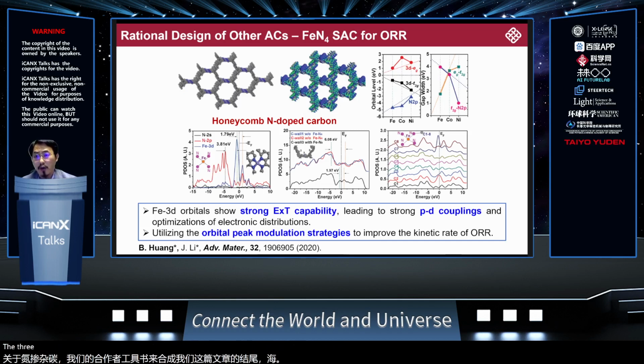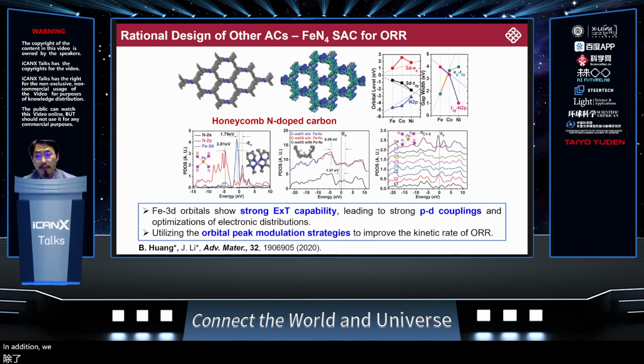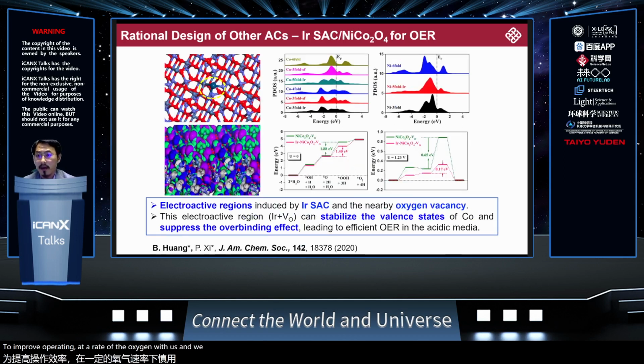The 3D orbitals of the iron show strong electron exchange and transfer capability. The pd coupling effect between the iron and the carbon support leads to electron distribution optimizations. In addition, we applied an orbital peak modulation strategy to improve the overall kinetic rate of the oxygen reduction reactions. And then we move on to the oxide system.